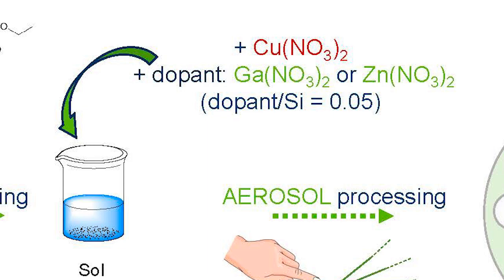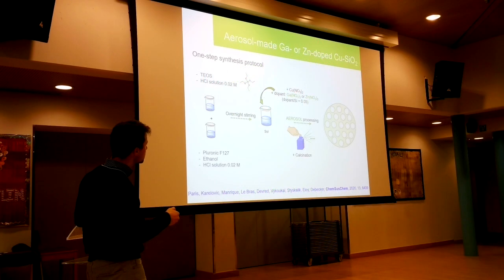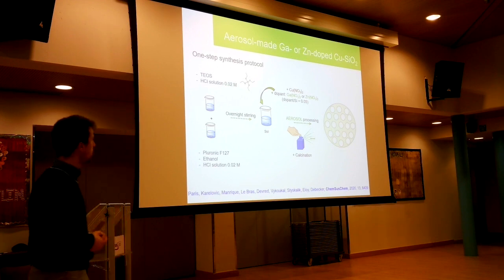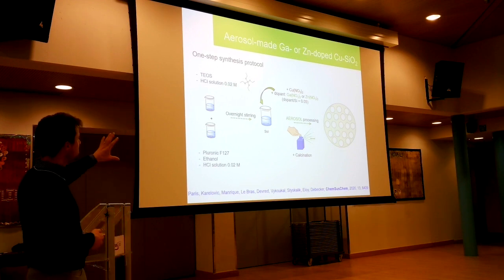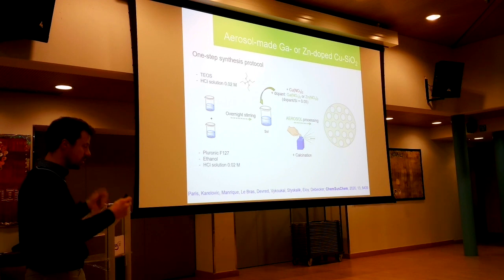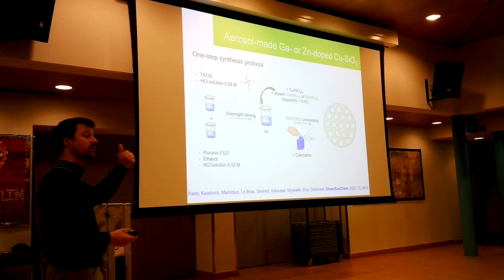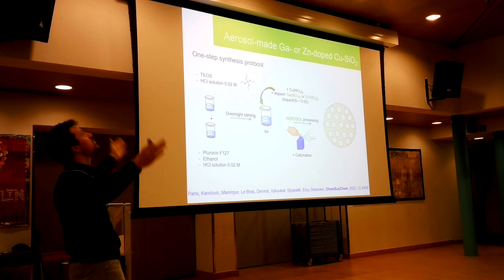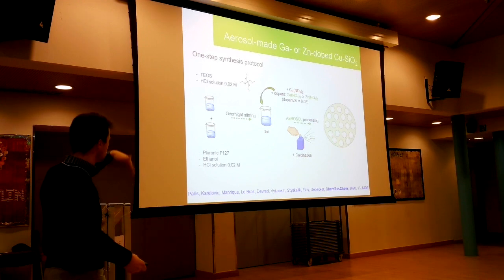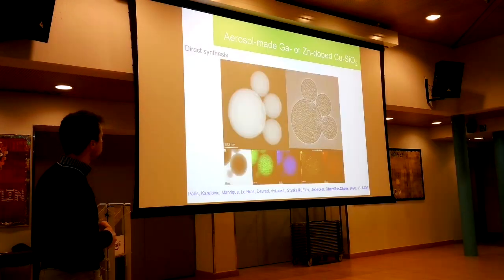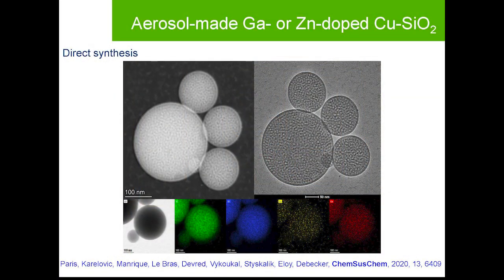So it's relatively easy. You just have to include here your copper nitrate, because you want copper in the end. And we were studying the effect of some dopants, gallium and zinc. Okay? So it's relatively easy. It's one pot. What you can do in the lab, just by spraying, drying, and collecting the support, you can actually do at the industrial scale, because with spray dryers of 30 meters high, producing tons an hour. These are the catalysts that we developed.